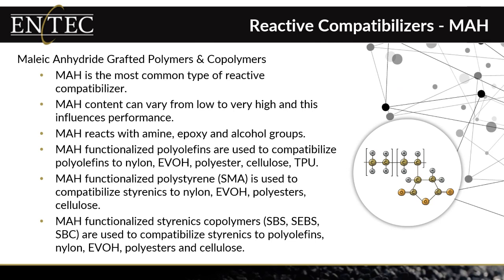If we look at the styrene maleic anhydride materials, these are going to compatibilize styrenic polymers to those polar materials like nylon, EVOH, and polyester. And then we have maleic anhydride functionalized styrenic copolymers. So these are things like SBS, SEBS, and other styrenic block copolymers. In addition to compatibilizing styrenic materials to polar materials, these can also compatibilize styrenic materials to polyolefins. So once again, we can see there's a range of products here that can be used to compatibilize different polymers to different polymers.